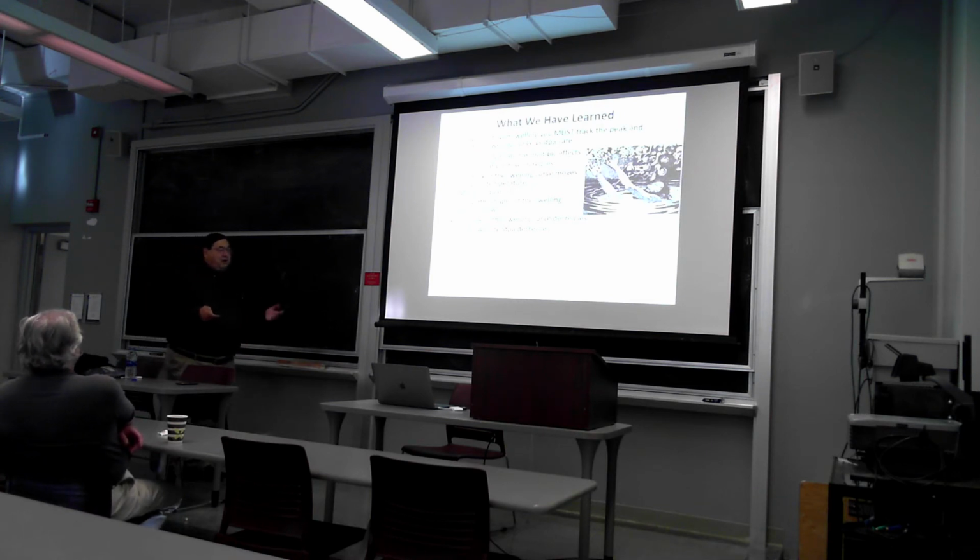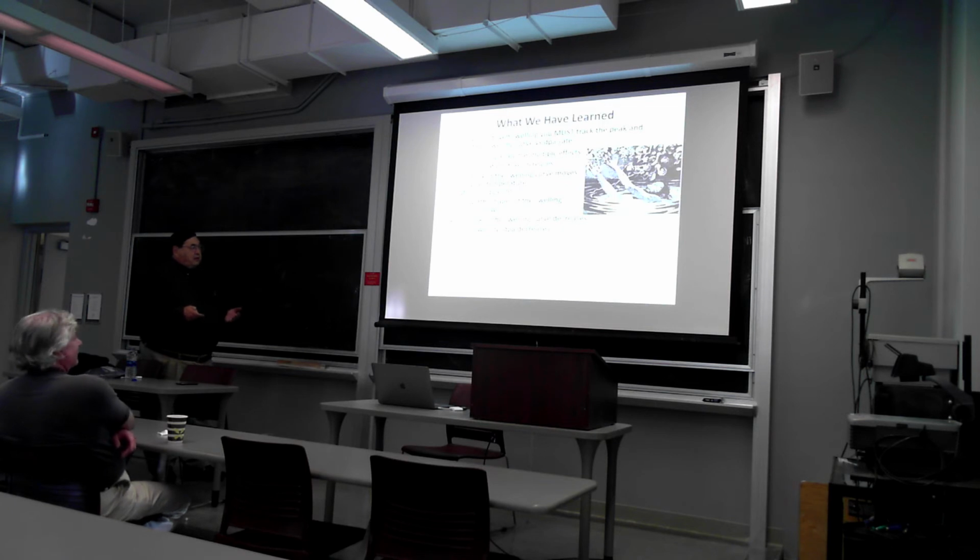So doing ion beam experiments is a non-trivial effort because you have to go to higher doses, higher temperatures, and of course, you have to do things over a wide range of dose rates, wide enough so that when you do the extrapolation, your experimental errors don't propagate so badly that you get meaningless data at low dose rates that are relevant to reactor conditions. So the incubation dose is both temperature and dpa rate dependent. We know that now.